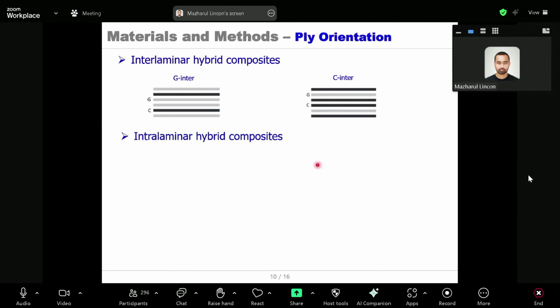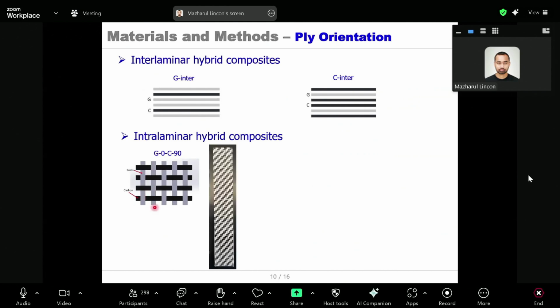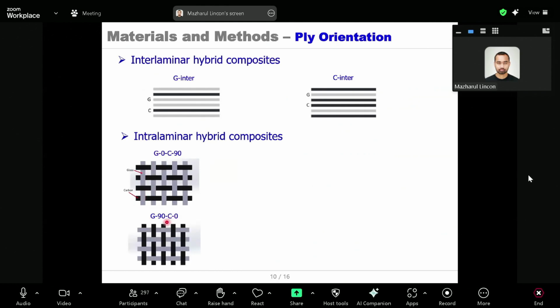For this intralaminar hybrid composite, 4 types of specimen are considered. The first one is G0C90, meaning the glass yarn will be parallel to the crack initiation direction. The opposite is G90C0, where the carbon yarn is parallel to the crack initiation direction.